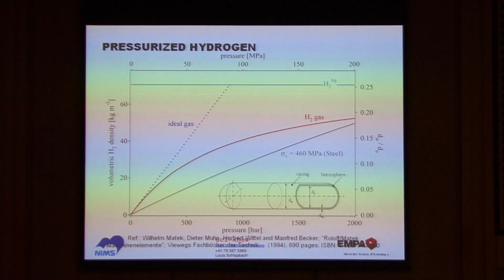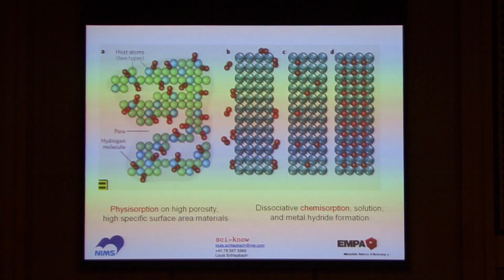The high pressure system, the pressurization, has its limits. In an ideal gas, when you double the pressure, you diminish the volume by half, but for all real gases this does not hold. The deviation from ideal gas behavior due to the eigenvolume of the hydrogen atoms or molecules becomes very significant already above 500 bar pressure, and it does not make sense to go much higher than the 700 bars or 70 megapascals used today. So that's a natural upper limit.